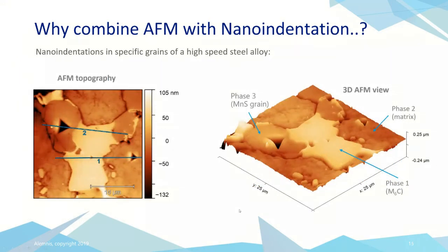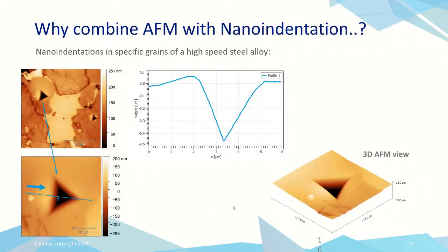So as Veronica showed earlier, some examples on high-speed steel, being able to zoom in on specific grains within a microstructure and then imaging those with extremely high resolution AFM. This is a very interesting technique. And we can see a couple more examples here. Taking a cross-section through an indent also tells us more about the pileup in a quantitative manner.